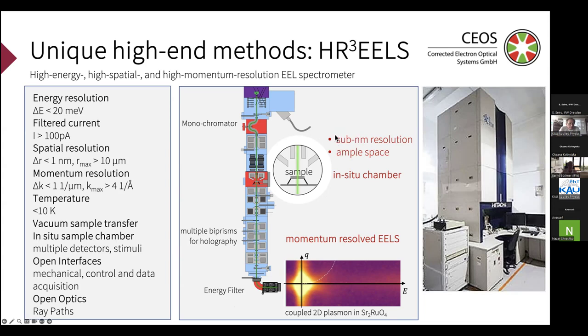Maybe not at the highest energy resolution, but of course with TEMs we have sub-nanometer spatial resolution, and you have a momentum resolution. So you can also measure the excitations as a function of Q. And that's something unique. If you combine this with low temperature, then it's a unique method which is currently developed here at the IFW. The first experiments are running now, first papers appear, but we are still improving the energy resolution.